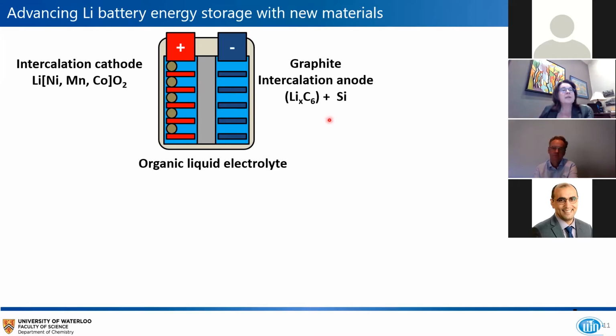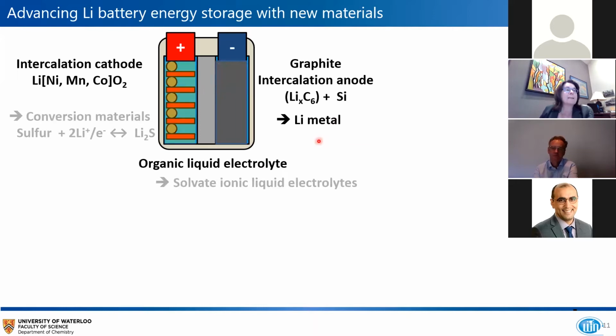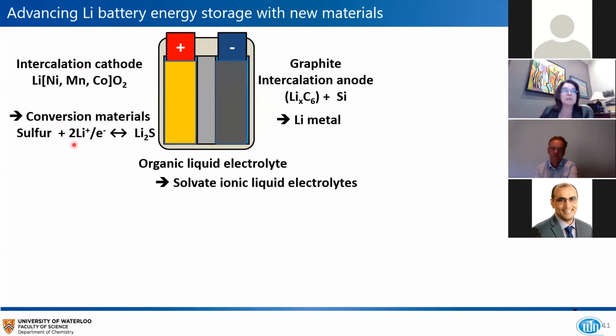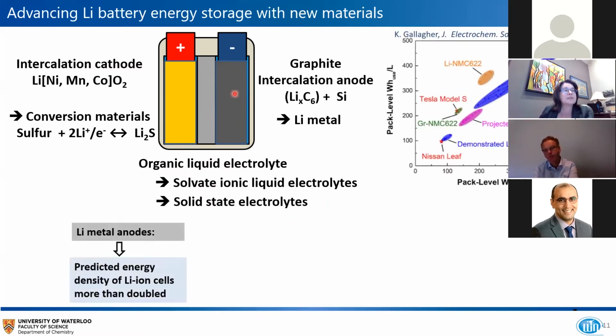And so it is anticipated that in the coming 5 years, perhaps longer, depending on how things move along, the negative electrode will be replaced with lithium metal. The positive electrode may be replaced with conversion materials that don't operate by intercalation, but by this conversion reaction shown here. And that will necessitate new organic electrolyte or just new electrolyte concepts. For example, solvate ionic liquid electrolytes that I'll be briefly touching on, and also solid state electrolytes. And if one can successfully implement a lithium metal anode, then even without considering alternatives at the positive electrode, the predicted energy density of lithium ion is more than doubled.